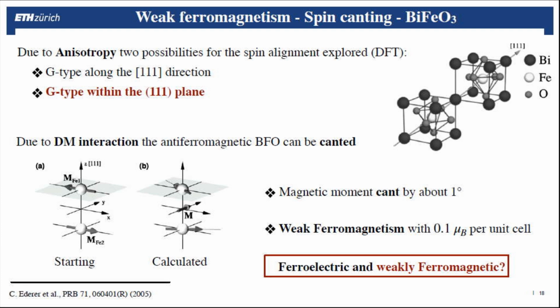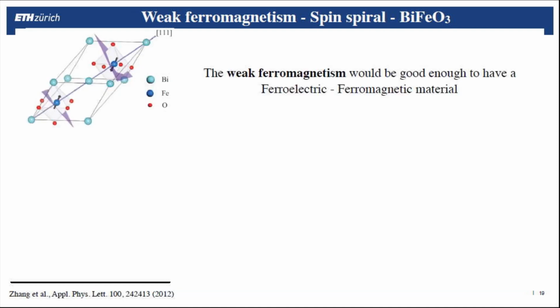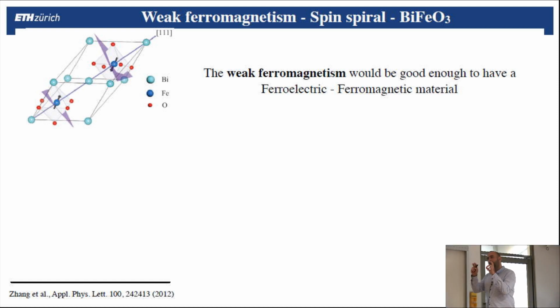But now we see that it has a small canting that would result in a small net magnetization, which would be good for application. So let's go a little bit further. And if we had this, then we would have a ferroelectric and ferromagnetic system.